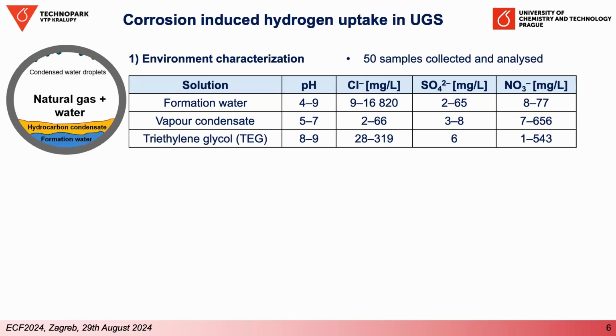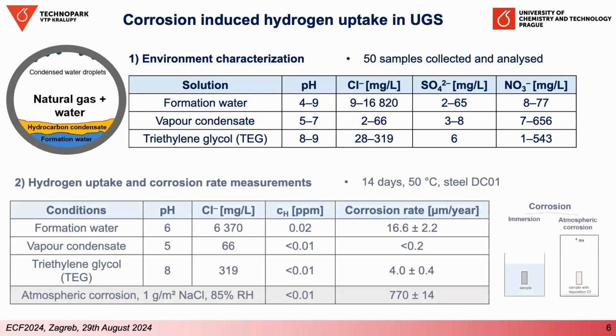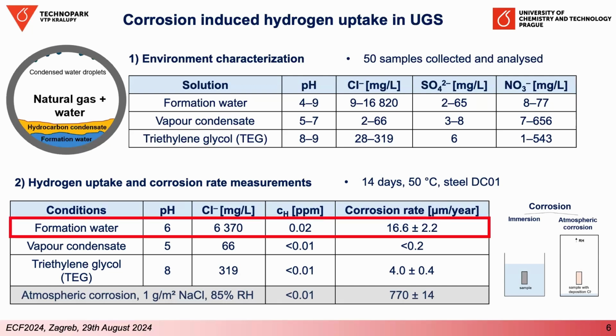what are the sources of hydrogen in the underground gas storages. So we received a lot of samples of the contaminants of 3 different types: formation water, vapor condensate, mostly hydrocarbons, and these glycols for drying. We did some characterization, but the most important here was the characterization of hydrogen uptake in this part. And of course, only the formation water was recognized as a source of a measurable amount of hydrogen in the steel, and it was connected with corrosion rate. We did a mass loss test here to evaluate the corrosion rate.